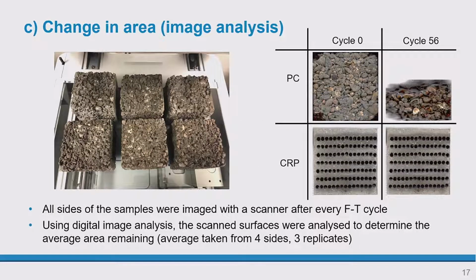Then we looked at the change in area. So we scanned the different samples on all of their surfaces and, through image analysis techniques, measured the area left after 56 exposure cycles. So this is the conventional system, the 30% sample at the start, and this is after 56 cycles, where you can see a significant area of it is lost. And at the bottom, we have CRP. And in case you were wondering, we didn't just copy and paste the same image twice. This is actually what the behavior was after 56 cycles.